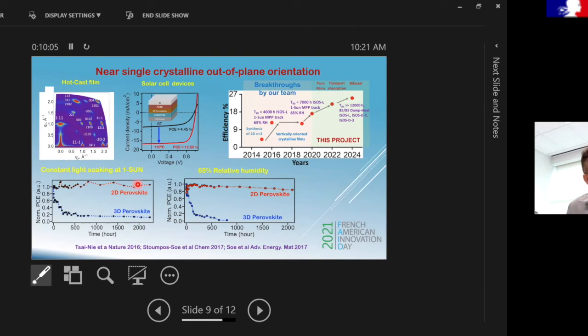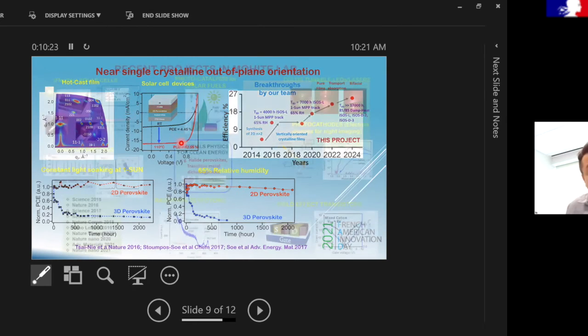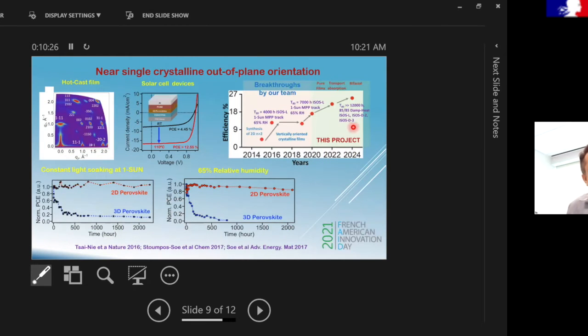This is a device which was put under continuous sunlight, and this went on for about 2200 hours without any degradation. This was another device at 65% humidity, and again, you see that these 2D perovskites are way more stable. Now, at that time, the efficiency of these devices was about 12%, which was sort of a record in itself. But now we are at about 18 to 19%.